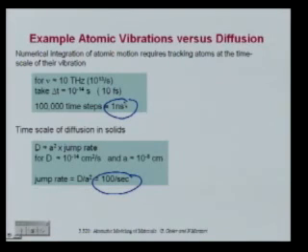Okay, you'll see similar phenomena. Like you could use dynamics to look at, say, surface deposition. Let's say molecular beam epitaxy or something like that, where you lay down layer by layer. If you actually do the math, in a real MBE experiment you tend to lay down about 1 layer per second. That's the order of magnitude. So you can actually never get that by direct simulation. So what do people do? Well, people do short simulations to extract useful information that they can then use in other models, okay, to get the real time scales that they want. And so that's some of the things we're going to teach you.